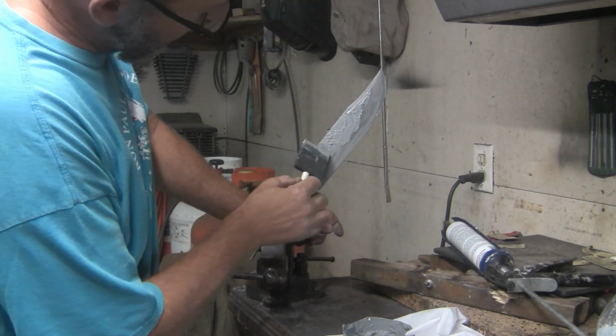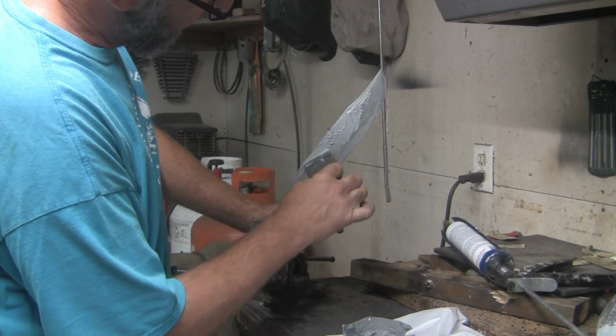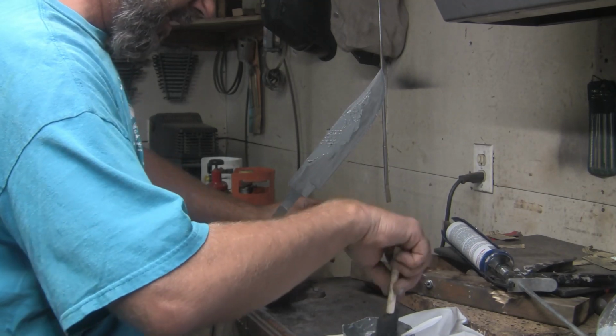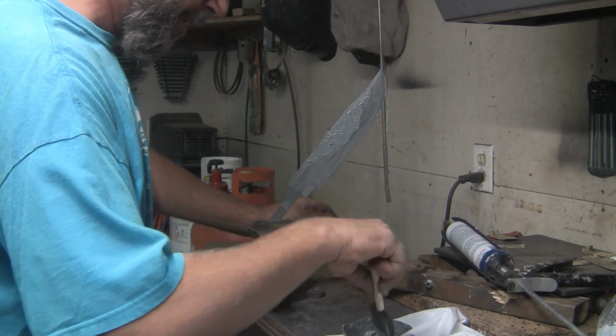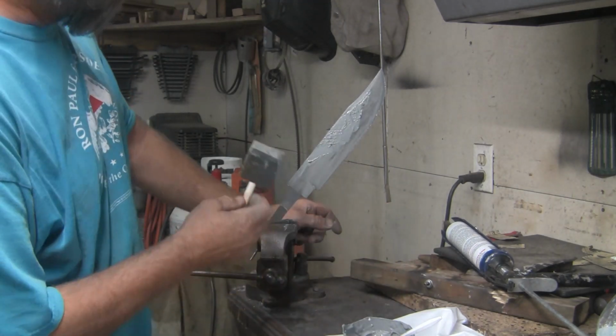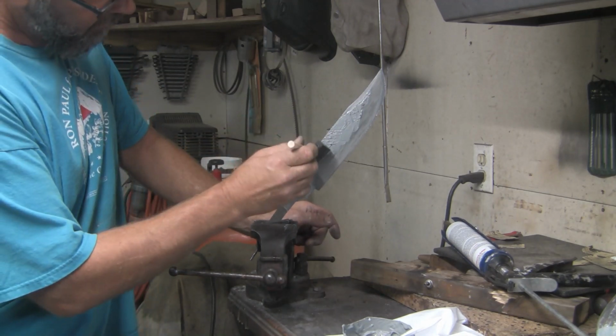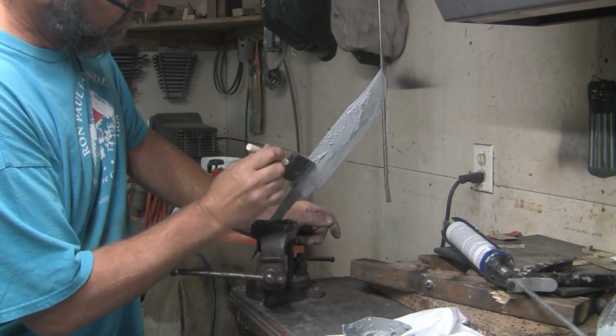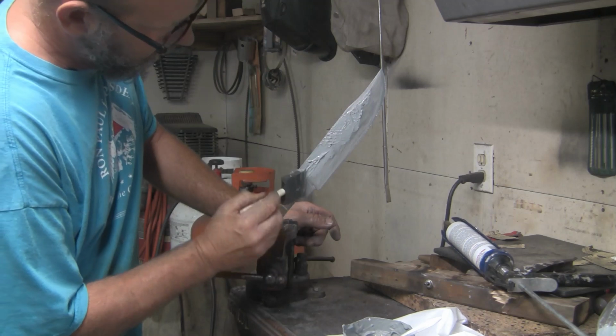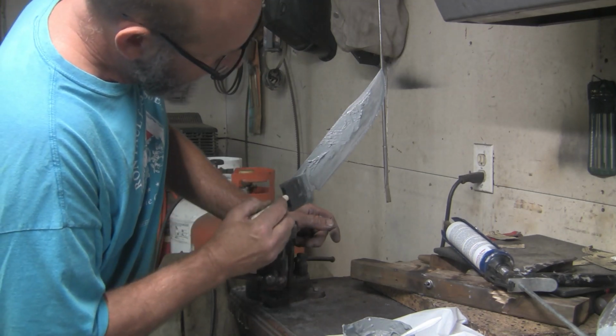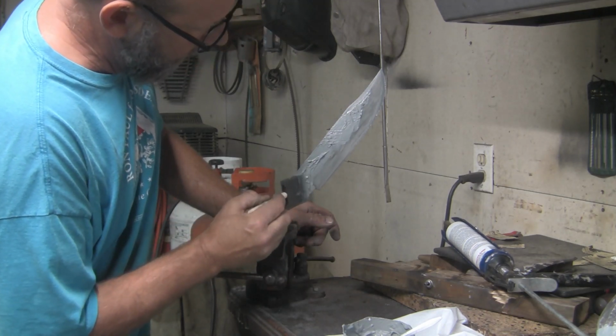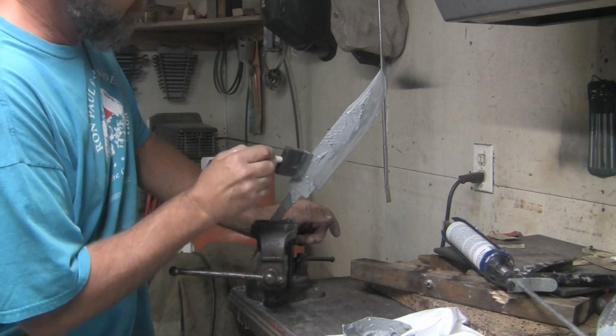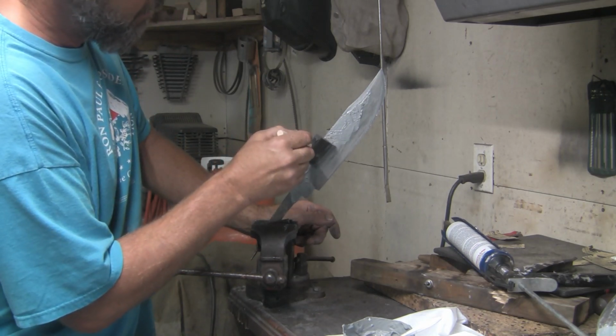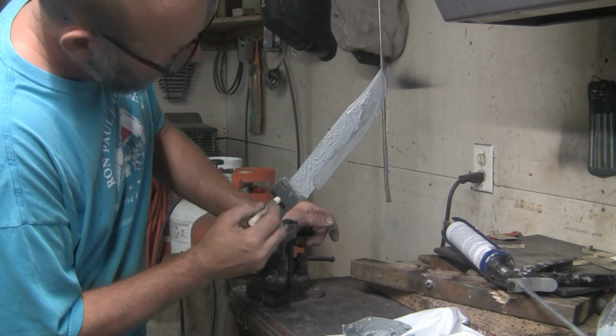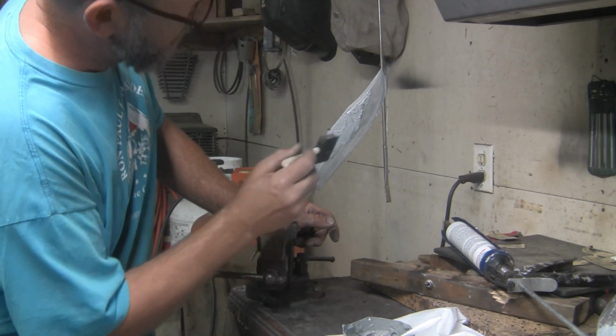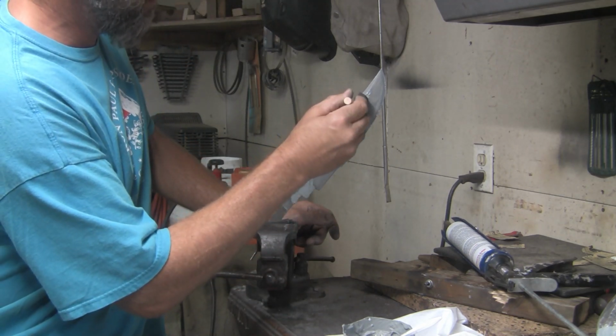And I guess the key here is got to get it pretty much even on both sides, so when it hits the quench, it doesn't cool down at such a rapid rate in a weird area that it would actually pull the blade over and cause a warp. So this may still be a little bit on the thin side. I may add some more,